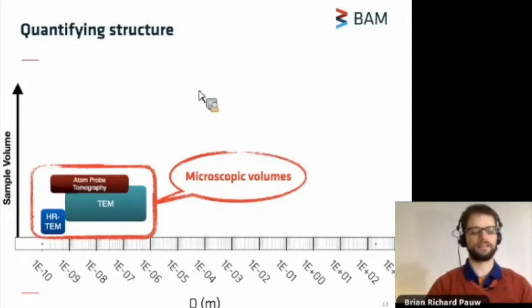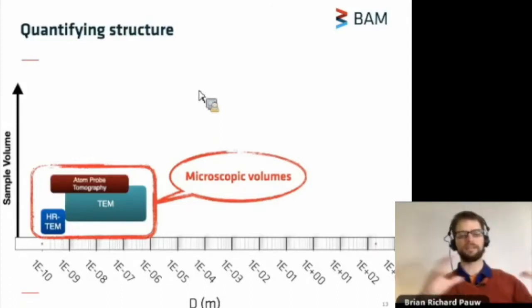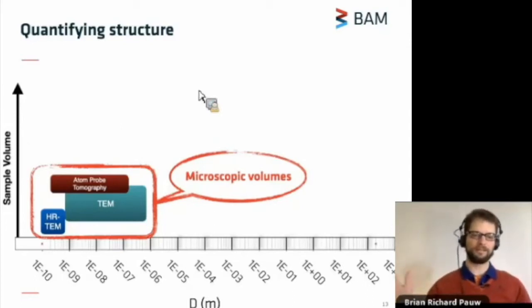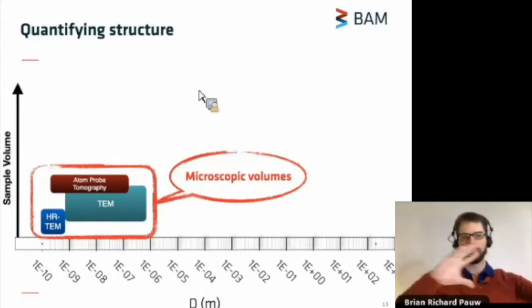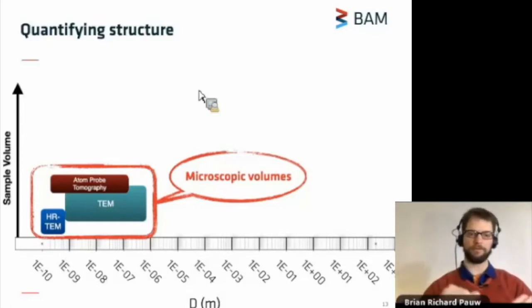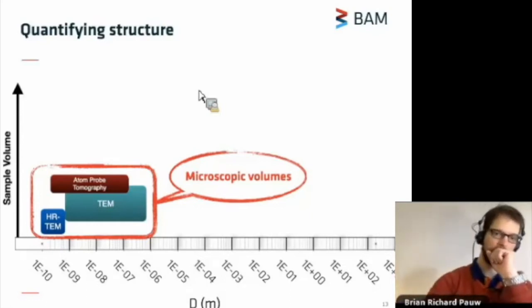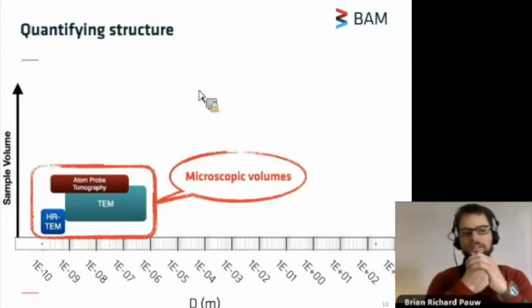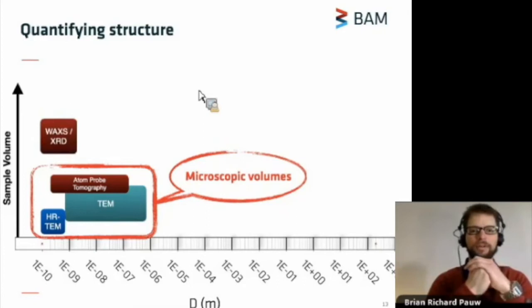I think it's an ablative technique where you take a needle-shaped sample and, by stepwise ablating your sample and finding out where the atoms came from that eventually land on your detector, you can build up a three-dimensional map of your sample. But it isn't until you hit the X-ray scattering techniques that you can really start talking about bulk analysis.